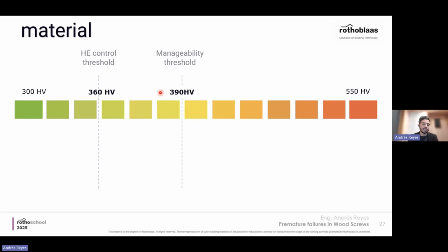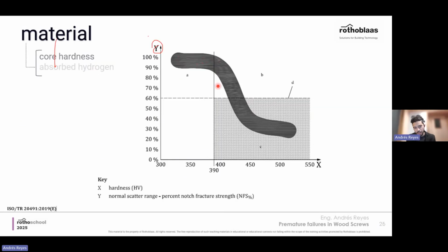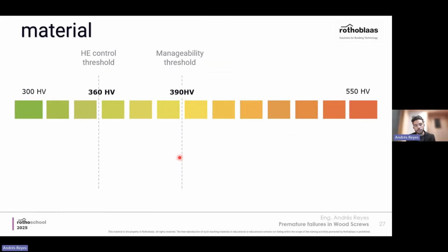Nonetheless, the standards approach is to set two thresholds, one at 360 and one at 390. Above 390 would be considered high risk, even if not necessarily a huge change, but of course we see here the decay of the performance. So it's understandable that there is a threshold at 390, and the other threshold is 360, where below 360, the norm says that the risk of hydrogen embrittlement is so low that in many cases, depending on what you're producing, you could even have no control of the hydrogen embrittlement parameters.